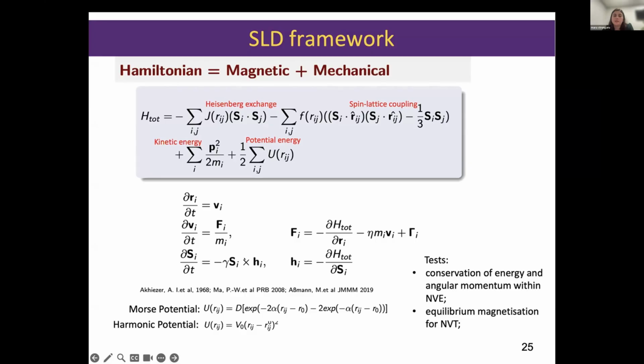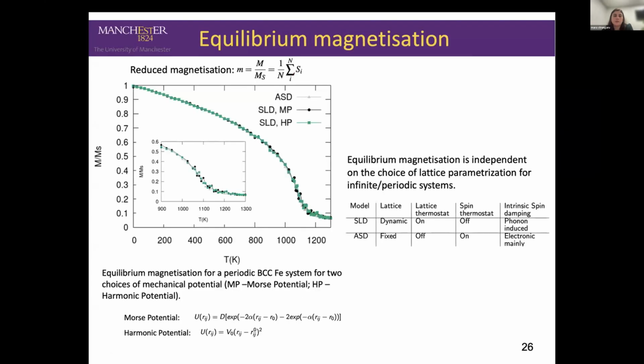What's interesting is that we can basically neglect the damping term in the Landau-Lifshitz-Gilbert equation, so we have just a precession term, since damping and dissipation will come intrinsically in our model from coupling to the phonon bath. Our model is able to pass relevant tests such as conservation of energy and angular momentum. And we are also able to use various choices of interatomic potential, Morse and harmonic potential. These are more simplistic potentials that we've implemented, however, it's possible to go to more complicated forms of potential, such as the embedded atom potential.